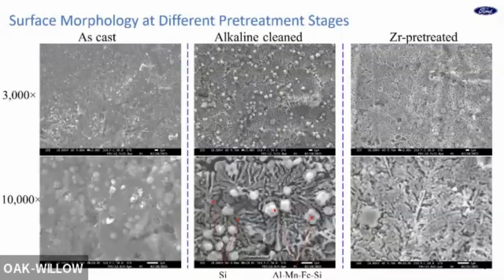showing some porous structure. If you look at the high magnification, you can see it's a layered structure, and it's mainly silicon. If you remember, this is more like the eutectic structure. It seems the aluminum layer dissolved and just left the silicon on the surface. Also, you can see some enrichment of the iron silicon particles. And after the zirconium pretreatment, you do see something deposited on the surface, especially if you look at the layer, the gap between the silicon layers is getting much smaller.